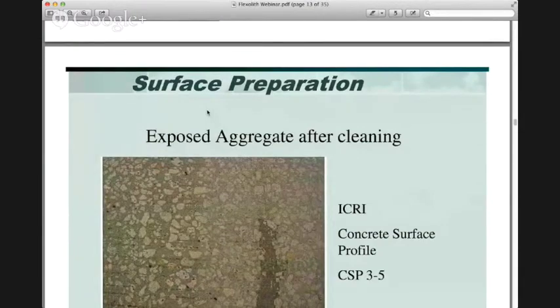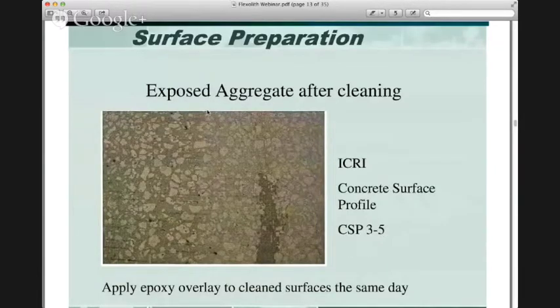This next slide shows you the exposed aggregate after surface preparation and cleaning, and what we're looking for here is a CSP, or concrete surface profile, according to the International Concrete Restoration Institute, of somewhere between 3 and 5. This gives us suitable texture and porosity to allow that epoxy to bond well to the concrete surface.